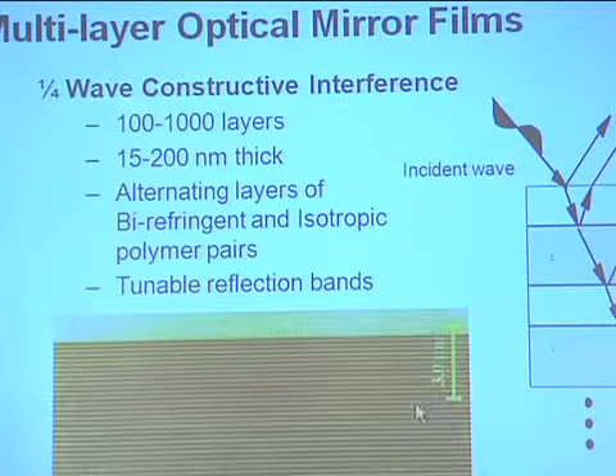And what's really unique about them is you can tune the reflection band by just varying the thickness of these layers. And a lot of people look at this and say, well, how many coating passes does it take to make that? And these are not coated, they're co-extruded. You take polymers, you co-extrude them together, and you make them into a film and you stretch the film. And so what we brag about here is we are able to control the layers of these films by the nanometer, but we make them by the mile. We literally make jumbos of film that are a mile long and several meters wide.